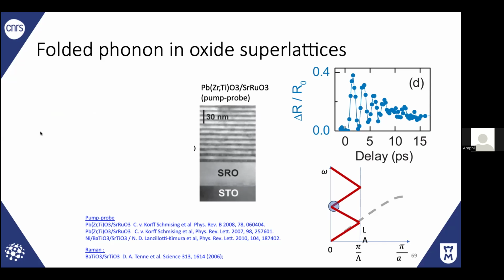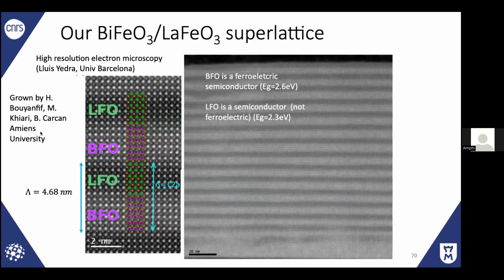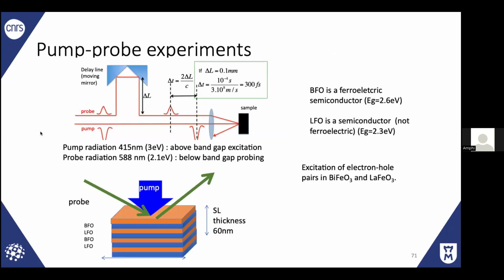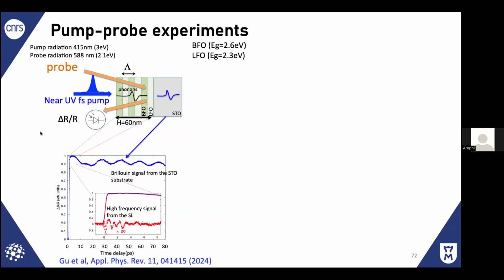And this is exactly what people observe in X-ray diffraction, for example, time-resolved X-ray diffraction. That works well. And we did it. We studied recently such an oxide, which is BFO, LFO. LFO is lanthanum iron oxide. And we did a pump-probe experiment. So when you do that on the superlattices here, you get such a signal.